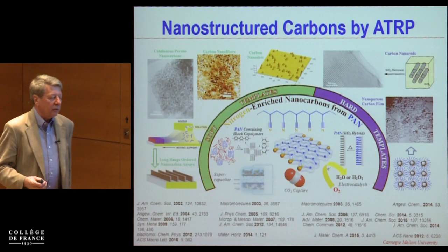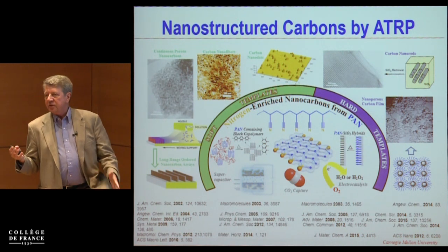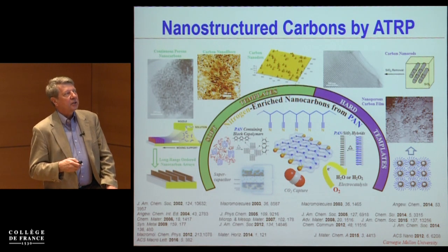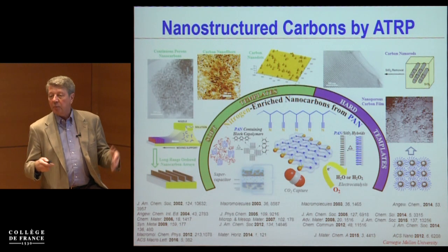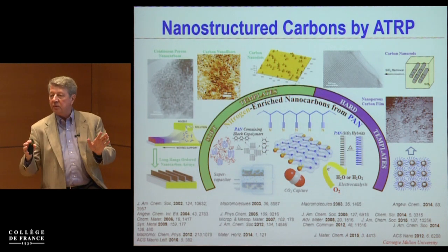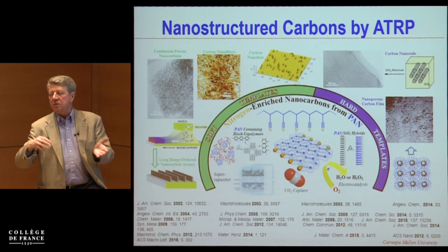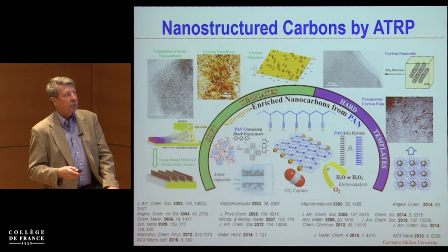So this brings me really to the idea of how you can use a templated process. We are interested in nanocarbons, carbons which are essentially nitrogen doped, and there are two ways to do that. One would be to apply hard templates, and this was one example which I showed you before, using mesoporous silica. But you could do exactly the same with silica particles, and then you can graphitize them, etch them, and then you have membranes filled with many pores which are replicas of these silica particles, whether it would be 15 nanometers, 20, 30. You can dial, you can also have a bimodal distribution, if you wish, of these silica particles.